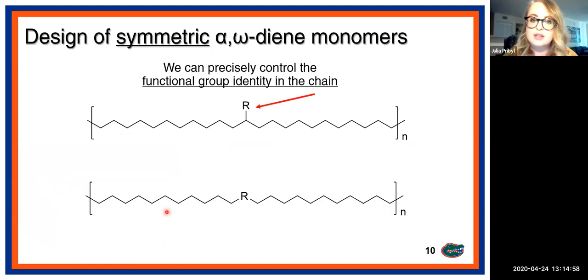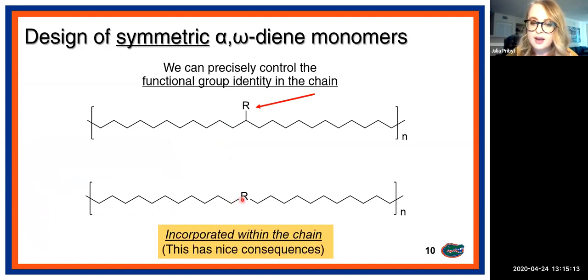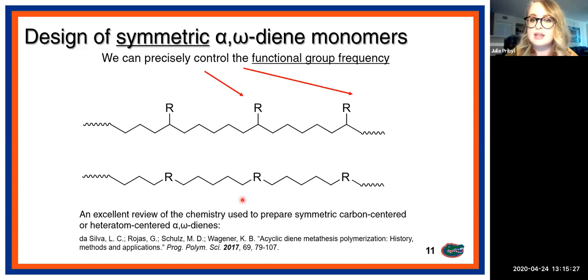So we can precisely control the functional group identity in the chain. A lot of synthetic work has gone into designing many different types of functionalities. And we can also incorporate the R group into the backbone of the chain. And this can have some nice consequences, particularly if it's a sulfone group, which I'm going to talk about a little bit later, but it can actually lead to very high melting point polymers, which is an area of my research. Another thing is that we can precisely control the functional group frequency. So we can make them closer together or farther apart.